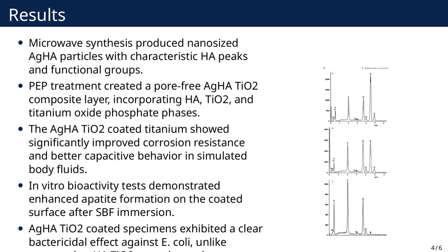The AgHA nanoparticles synthesized by microwave processing exhibited characteristic HA diffraction peaks in XRD, indicating nano-sized particles. FTIR spectra confirmed the presence of phosphate and hydroxyl groups, with some carbonate ions present due to reaction with atmospheric CO2. TEM micrographs showed needle-like AgHA particles with lengths of 60 to 70 nm and widths of 15 to 20 nm.